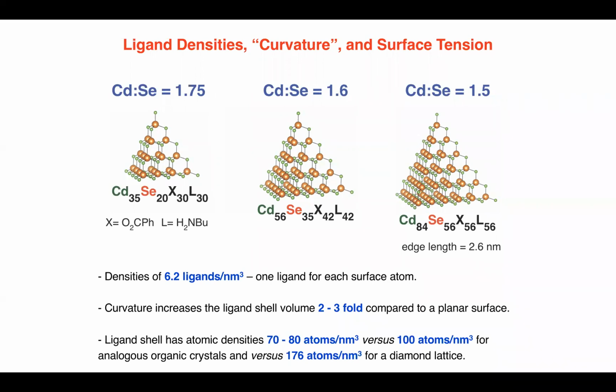But in the sort of idealized pyramid, you have stoichiometries that are almost totally cadmium enriched. And that ratio down here at this very, very small size approaches 2. So you can get a 2-to-1 kind of a ratio when you're really tiny, and then it drops from there. Another fun fact, this is 2.6 nanometers, getting into decent sizes. That's a sort of useful number to know. 2 nanometers is about where things begin to be molecular.